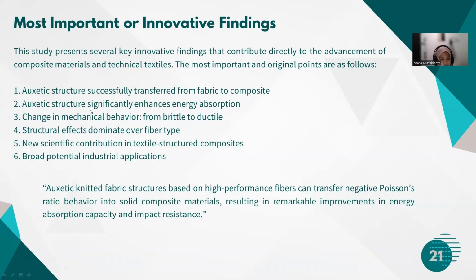Auxetic structures significantly enhance energy absorption, and the innovation is to demonstrate that geometry-driven design can drastically improve composite mechanical performance without changing the base material, and change in mechanical behavior from brittle to ductile.